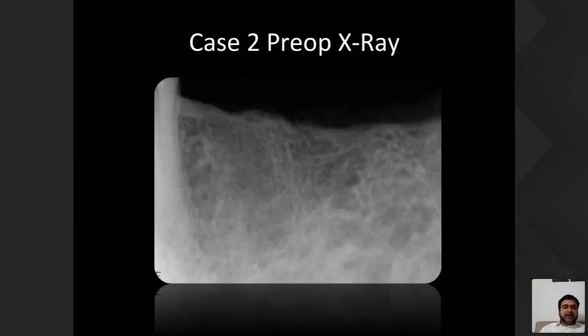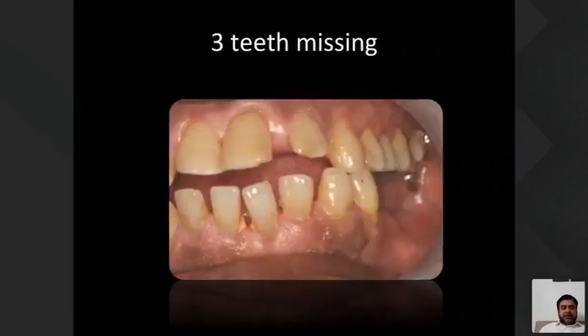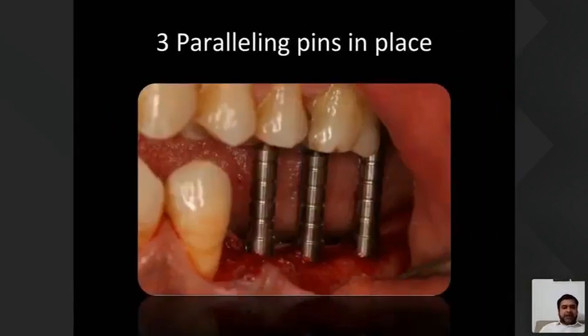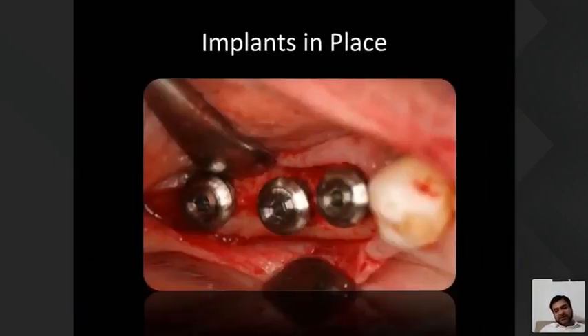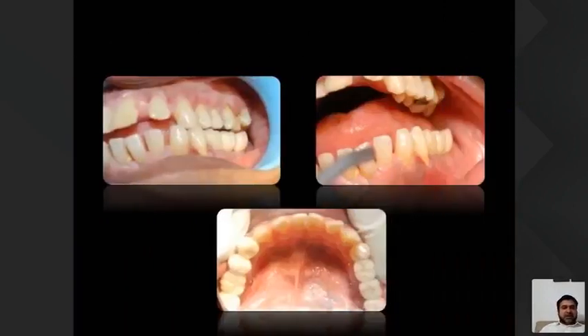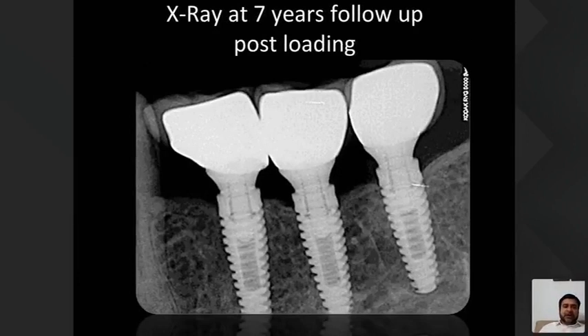This is the preop. 3 teeth missing right here. 3 paralleling pins in place after osteotomy was performed. Implants in place. So this is the final prosthesis. And this is what Dr. Naresh Bhatnagar had shown you initially. This is a picture which is a 7-year follow-up of post-loading. You can see how beautifully the crestal bone is maintained throughout these implants, even after 7 years of loading, where 1 to 1.5 millimeter of bone loss is also considered as acceptable after a year or so.